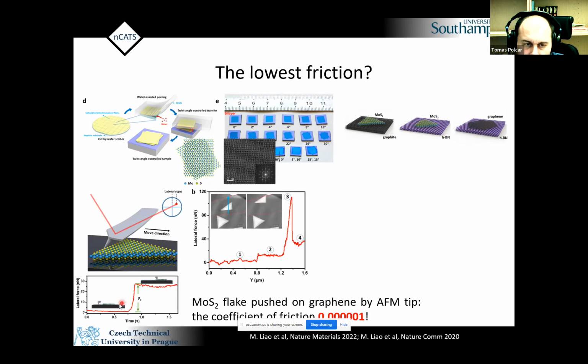And we can measure the force. This is when you slide before you hit the flake. Now I hit the flake, of course, the force goes up, and now I'm pushing the flake. So this difference is the genuine force of the flake. And this is beautiful here, because you see that this flake is moving on graphite. There is no other material, and I can directly measure the force. The only load here, of course, is the adhesion force, which is quite high for this type of material. So this is how we measure what I call genuine friction. And this is one way to do this.